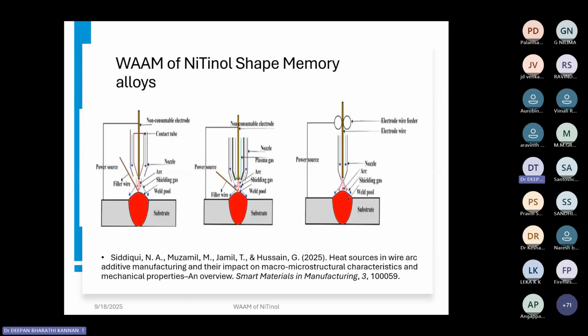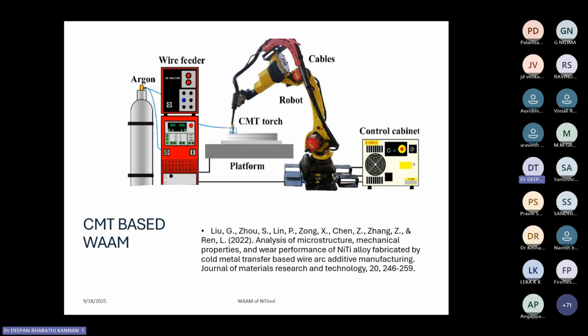So if you are interested in depositing at a faster rate, then wire arc additive manufacturing should be one of the preferred processes. Another advancement with respect to wire arc additive manufacturing is that a lot of advancements have constantly been made with respect to the power source to minimize the overall heat input so that the thermal damages are minimized. Like how we do with respect to welding, people have explored cold metal transfer arc welding for exploring the wire arc additive manufacturing of nitinol shape memory alloy.